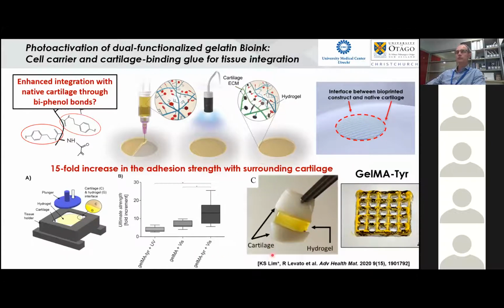Again, work done with Riccardo and Khoon, where we can try and show that in the presence of light, we can also get what we think is cross-linking between tyrosine-tyramine groups. So by incorporating tyramine, we can also get cross-linking with native tyrosines within surrounding articular cartilage. This shows two cartilage biopsies that have been adhered together using a dual functionalization process for cross-linking our hydrogel, but also binding surrounding native tissues, which show that we get a 15-fold increase in the mechanical properties compared to just photo cross-linking GelMA alone.